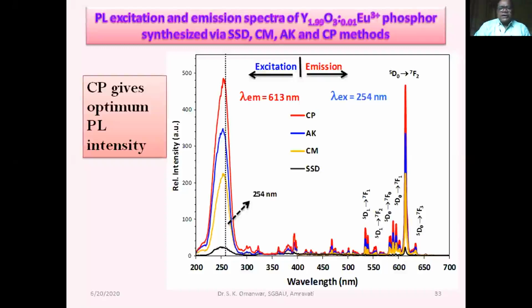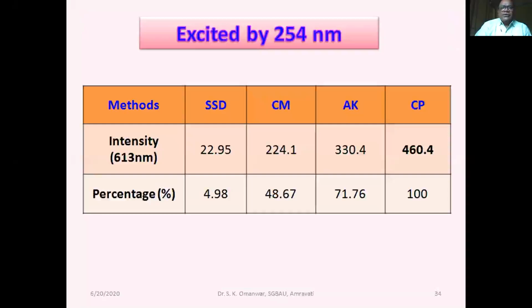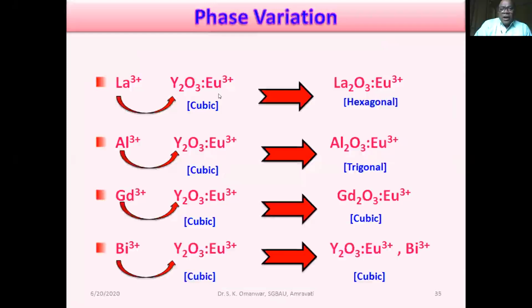And we try to understand as Y is replaced by La. Y is replaced by La, Gd, and Bi. If you go for a simple cubic structure, and once you try to replace with La, the cubic structure is getting changed to hexagonal, and that is what the stretching does, and this stretching might change it to hexagonal. Here cubic is getting changed to trigonal. Here there is no shifting of excitation because both are having the same, and here this also.